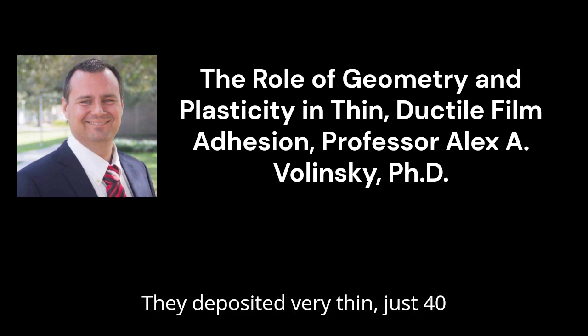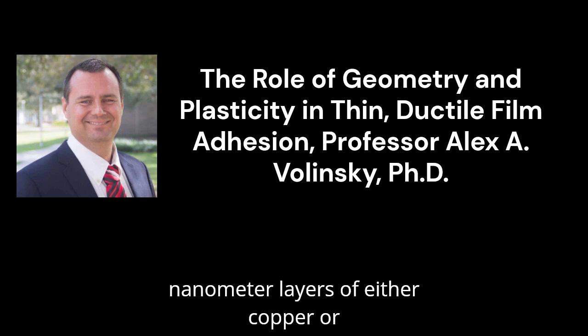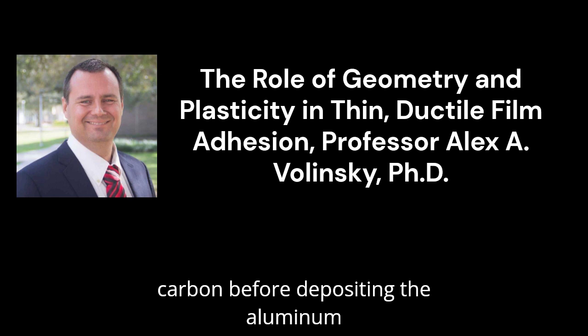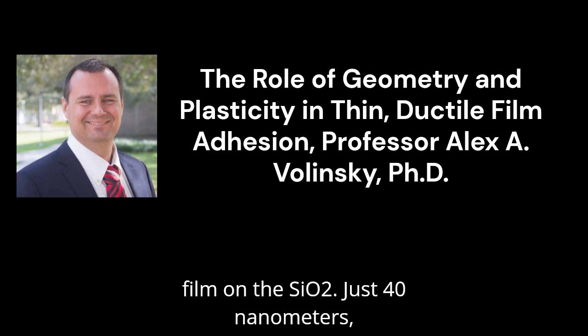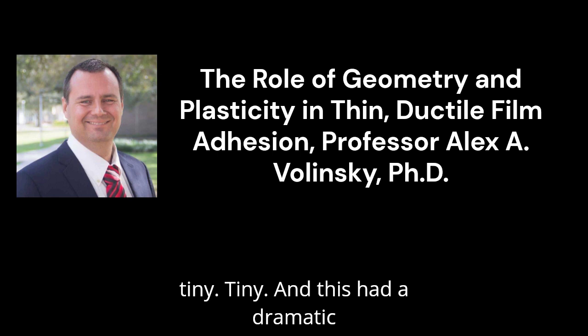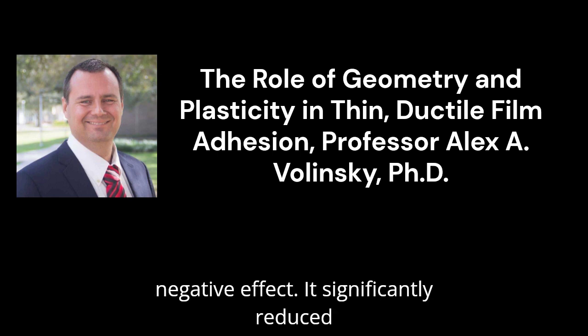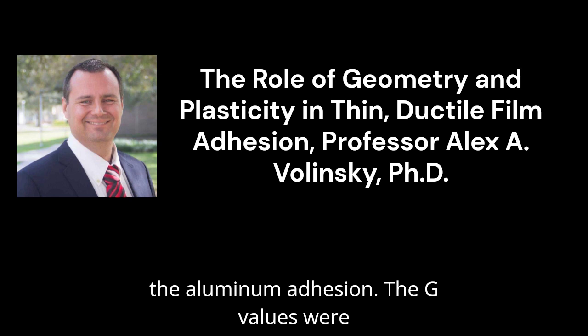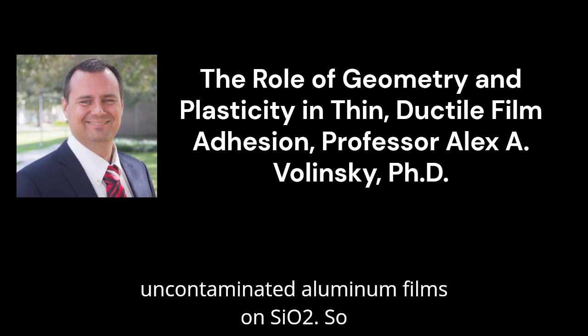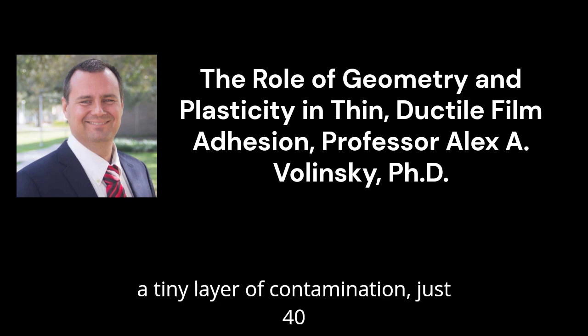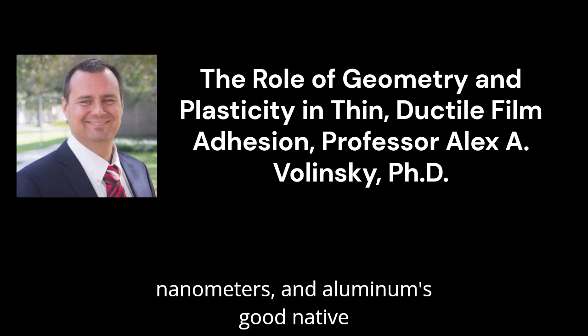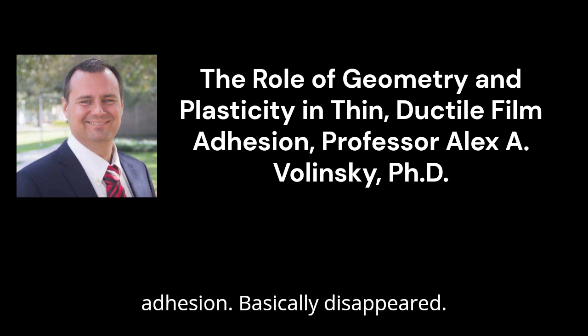They deposited very thin, just 40 nanometer layers of either copper or carbon before depositing the aluminum film on the SiO2. Just 40 nanometers, tiny. Tiny. And this had a dramatic negative effect. It significantly reduced the aluminum adhesion. The G values were much, much lower than for the uncontaminated aluminum films on SiO2. So a tiny layer of contamination, just 40 nanometers, and aluminum's good native adhesion basically disappeared.